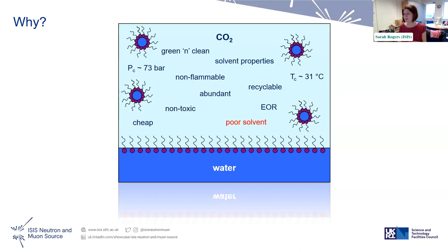It's recyclable. So the idea is you do your measurement under supercritical conditions, you let the pressure off, the product falls out, and then you can reuse the CO2 afterwards. It's cheap, non-toxic. And you can use it for things like enhanced oil recovery. But the big problem is that CO2 is actually a really poor solvent. It's actually not very good at being a solvent.